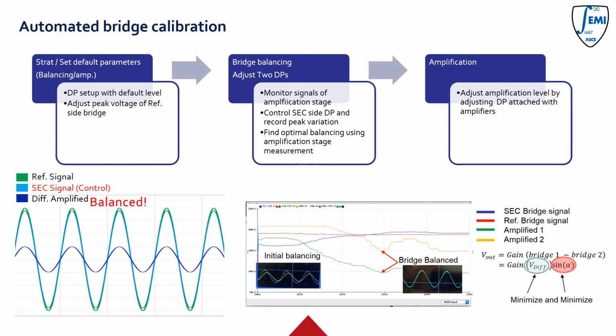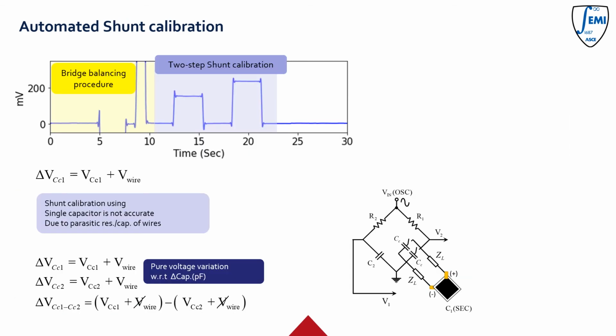Using the digital potentiometer, we control the SEC side signal and measure the variation of the peak amplitude of the first amplifier. You can find a convex point which shows the best balancing setup. After that, the amplification level was adjusted to the maximum possible gain level.